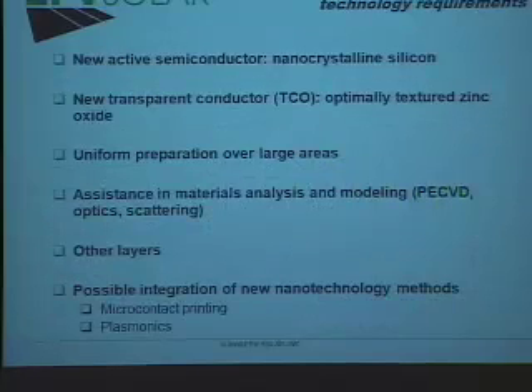So we need the high performance transparent conductor, amorphous silicons, and other layers, intermediate reflectors, and nanocrystals. Those are the sorts of things we are working on. If I break it down into the two main things that we need: nanocrystalline silicon, and an optimally textured zinc oxide transparent conductor. We need to be able to make those things over large areas, square meters at least.